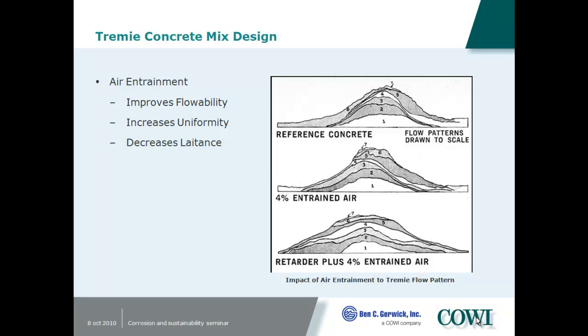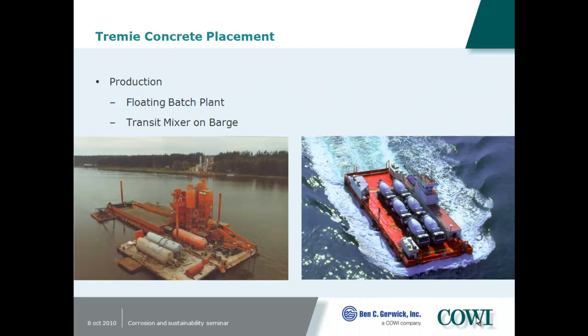So here's air entrainment. We did have, I think, up to 6 to 8% air entrainment here. As you put in air entrainment, you can take water out and still maintain the same workability. So it can be cost effective in that regard. So even though we don't have much of a freeze-thaw problem under the river, it can still improve workability. So you can see it can actually produce a little bit better flow patterns.